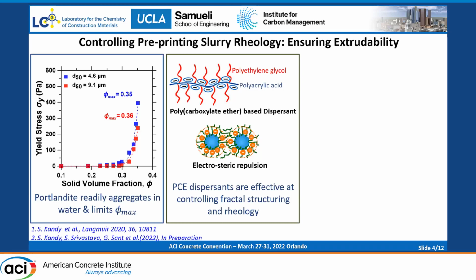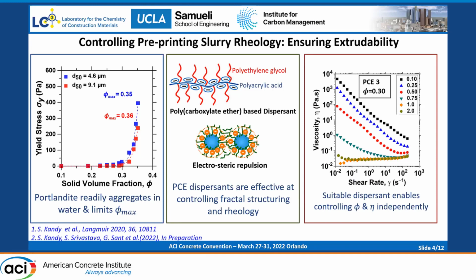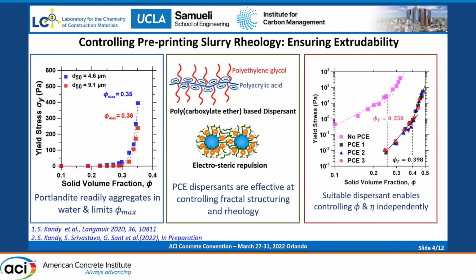With this, we'll be able to reduce the viscosity of the suspensions. We can go from a strongly shear thinning suspension to an almost Newtonian response by varying the dispersant fraction, and also we'll be able to increase the solid volume fraction in the suspensions from 0.3 to 0.5 without any significant increase in the yield stress or the viscosity.